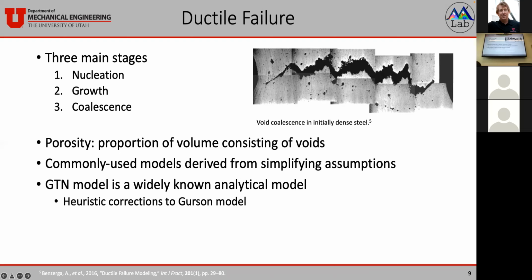So ductile failure, there are three main stages: nucleation, growth, and coalescence of voids. Here on the right, I've shown void coalescence. You can see there's a crack. This is in initially dense steel. You can also see these smaller voids. Some have grown larger. And the very small ones have nucleated on particle defects or inclusions.